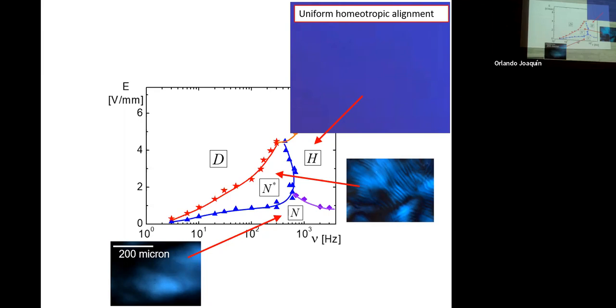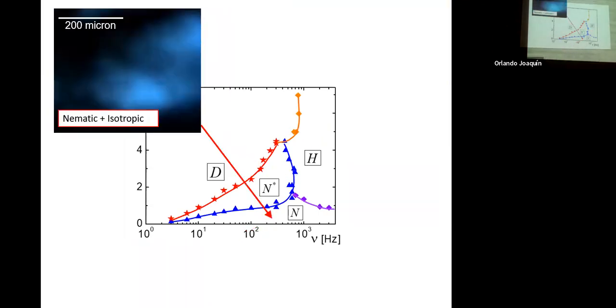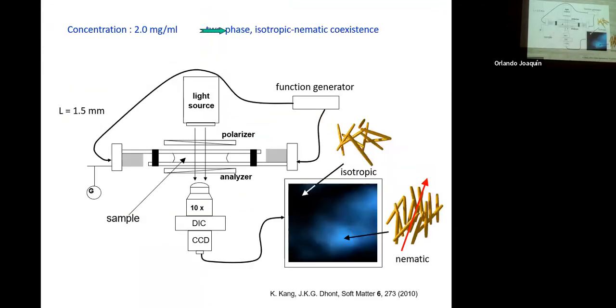Yeah, these are optical images, or the Fourier images, directly from the microscope. Okay. So the field of view is about 400 microns. So it's a very simple experiment. Right? So you put two electrodes, which are transparent, and you put them between both polarizers, a light source, and you make a recorded image.